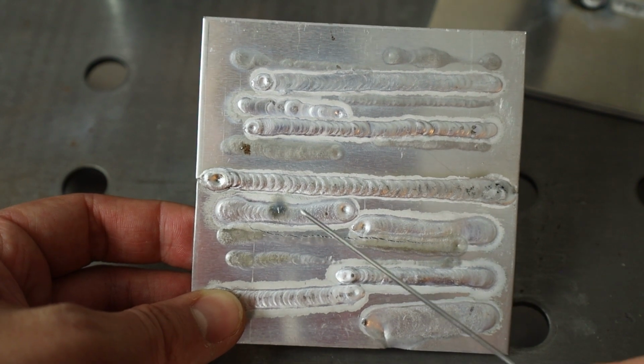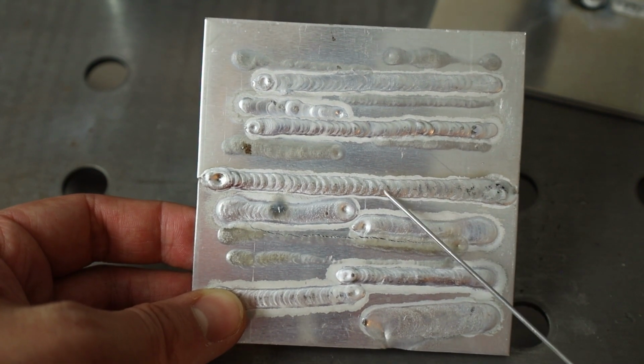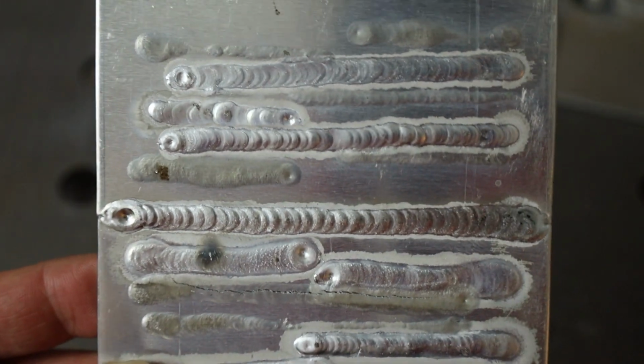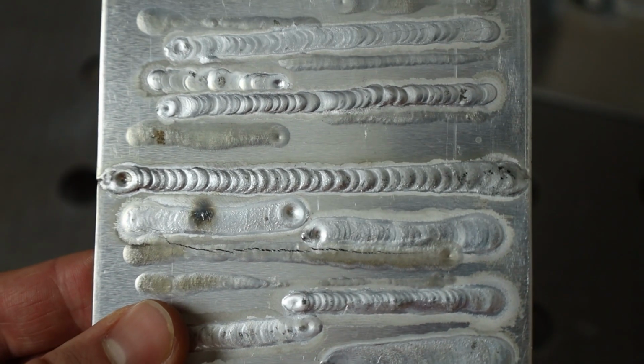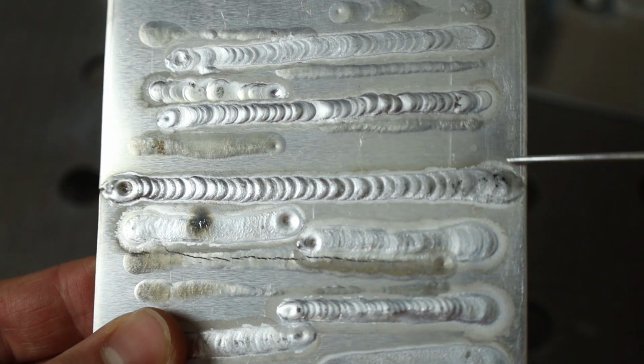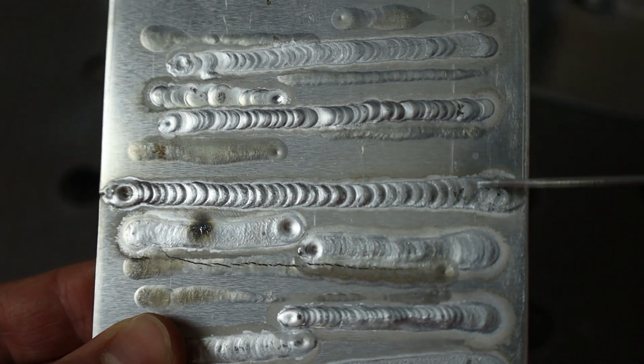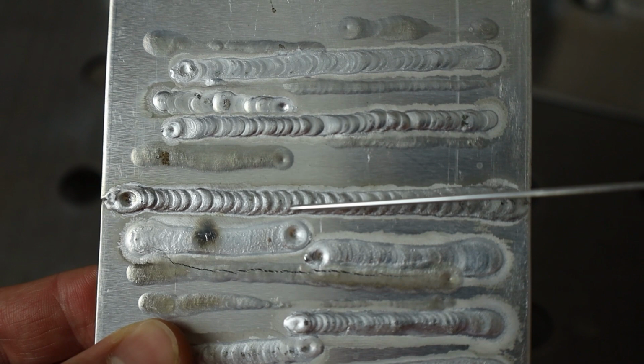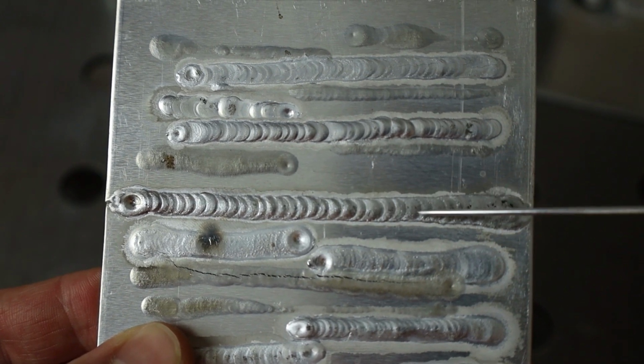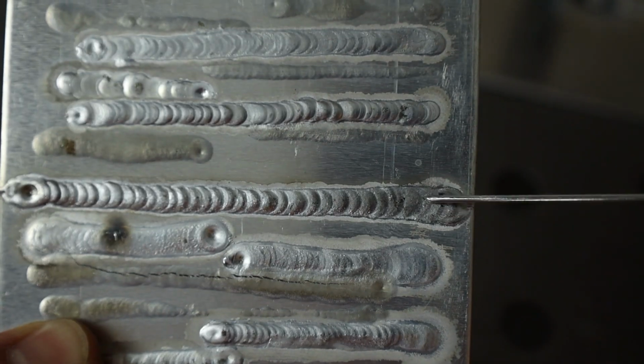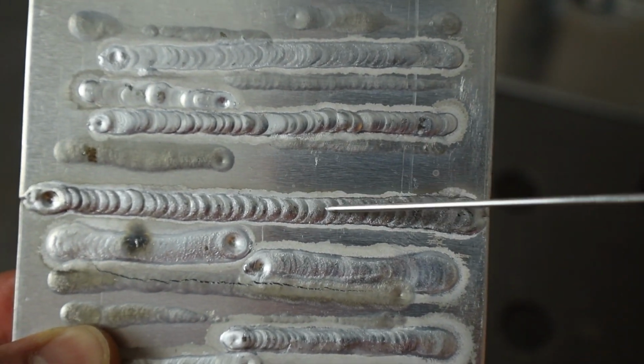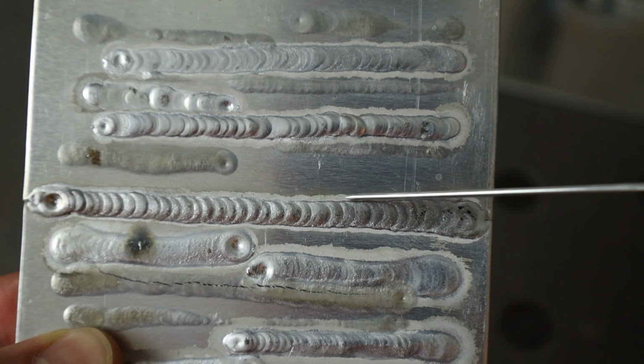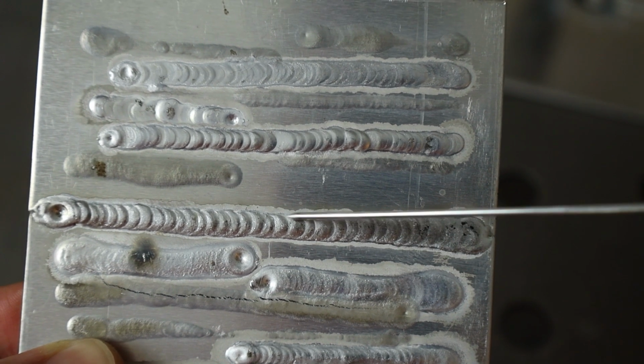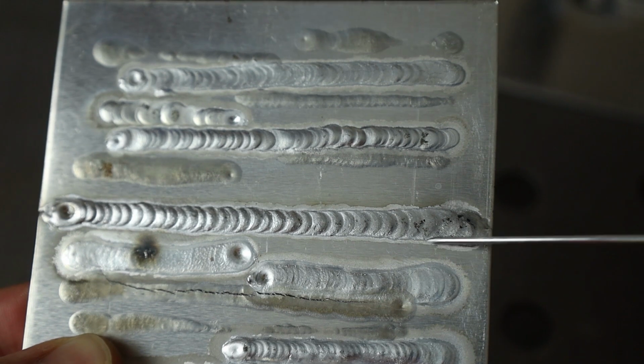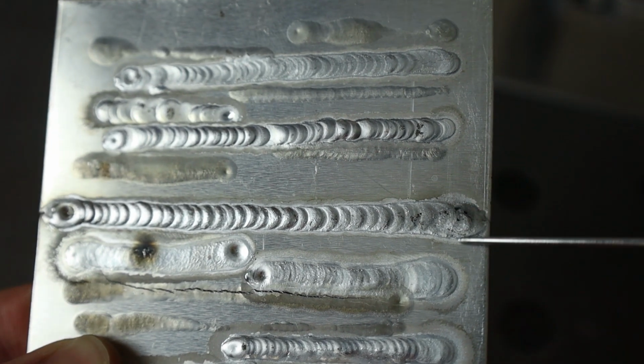Typically you'd have your machine set to 62, 63, somewhere in there. If we take a look, you can see that I started out too hot. You can see how wide this is at the beginning before I get into my rhythm and it starts to become somewhat decent. And you can see how flat that is, as opposed to over here, you can actually see the dab profile. As I was going along, you can see where I was adding filler rod, but because of how hot it was right here at the beginning, there's not really a whole lot of definition there.